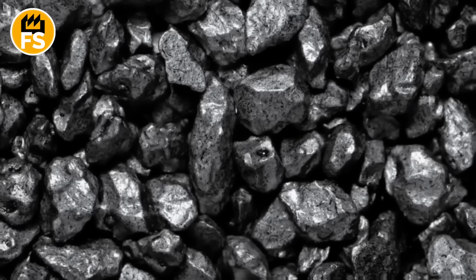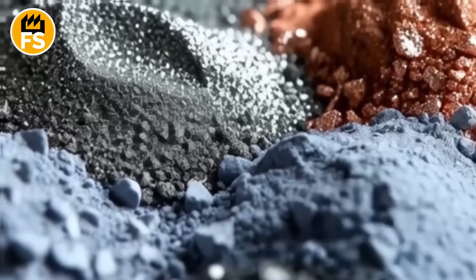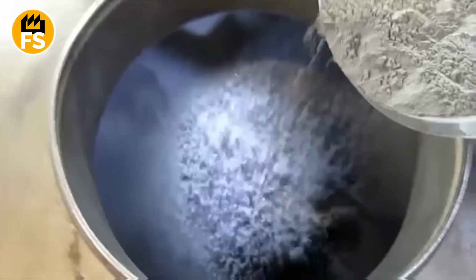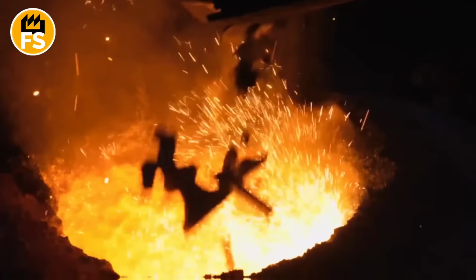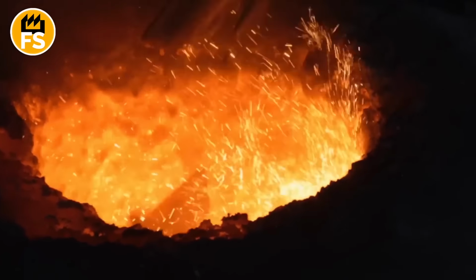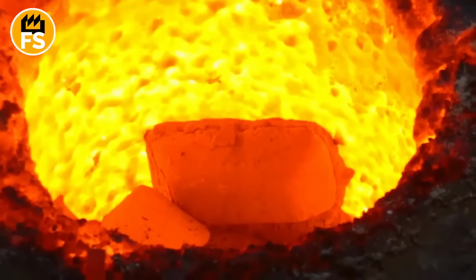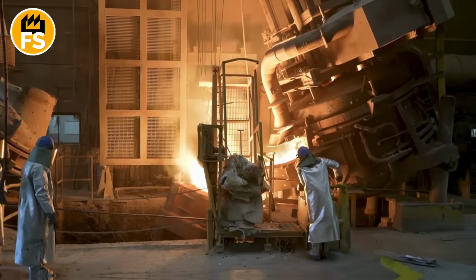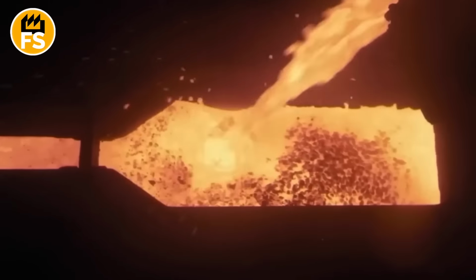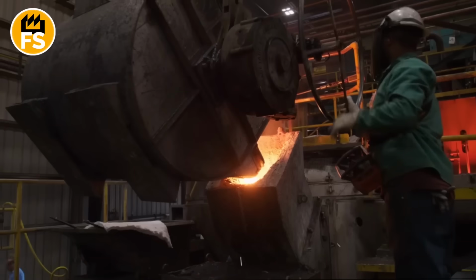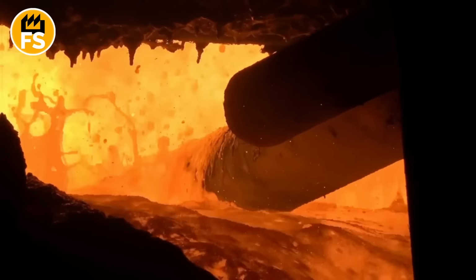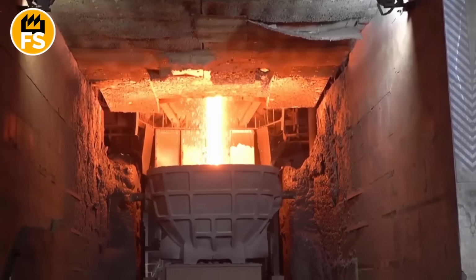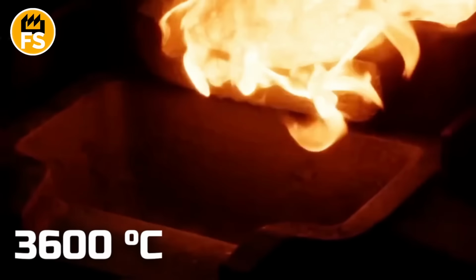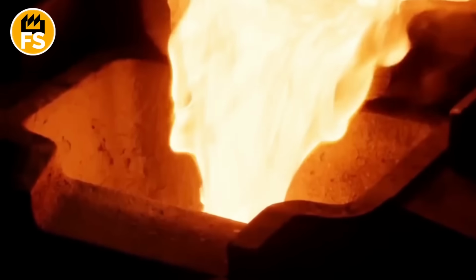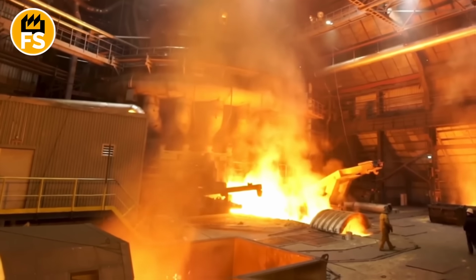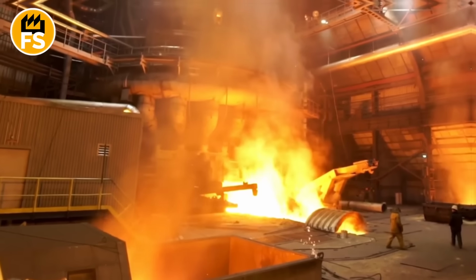The process begins with charge preparation. Vanadium pentoxide is mixed with reducing agents, typically aluminum or silicon, and iron in strictly defined proportions. Next, the mixture is loaded into crucibles or electric furnaces, where conditions are created to reduce vanadium from its oxide state. Temperatures in the reaction zone reach over 3,600 degrees Celsius, and it's at this moment that one of the most intense stages in the entire production line occurs.